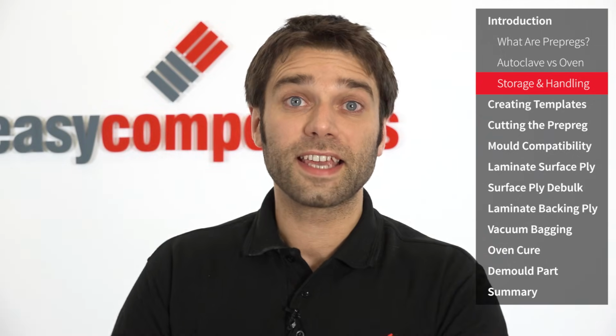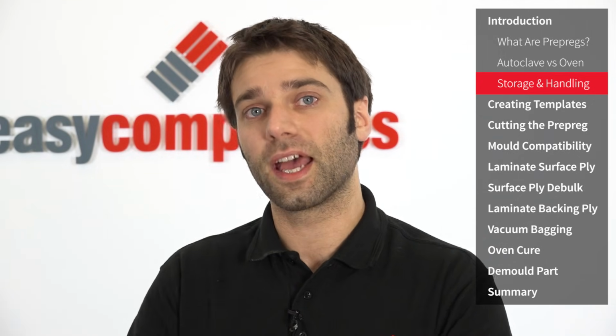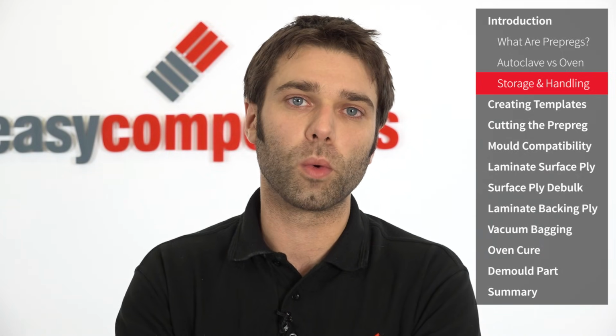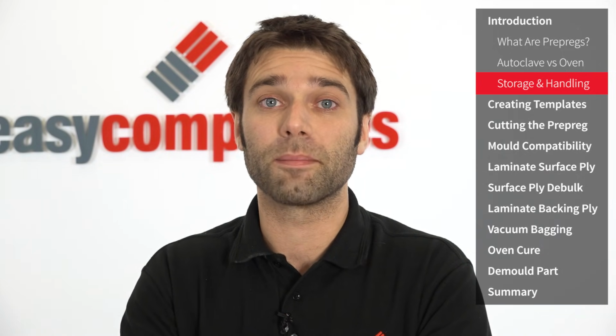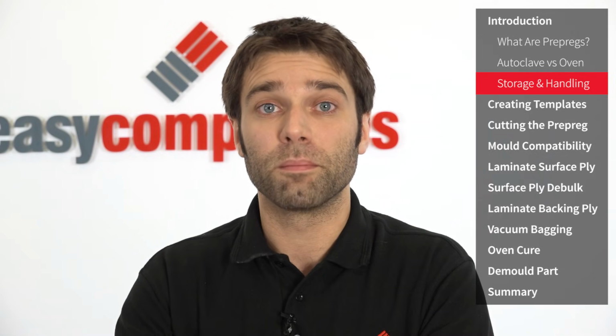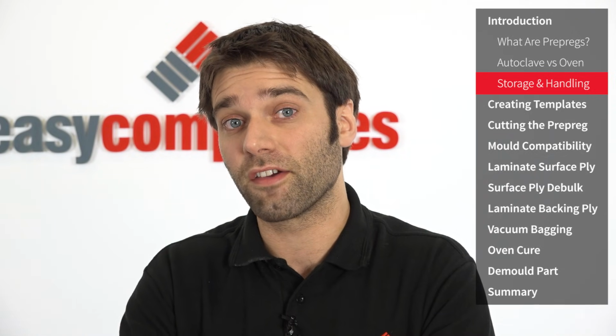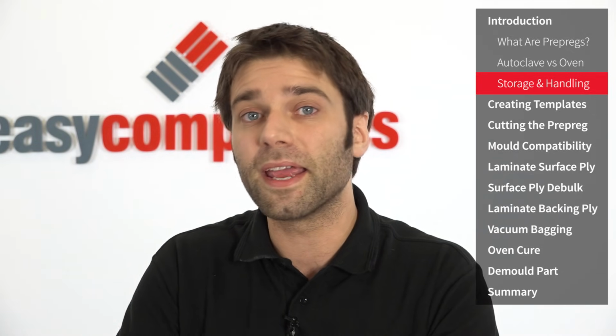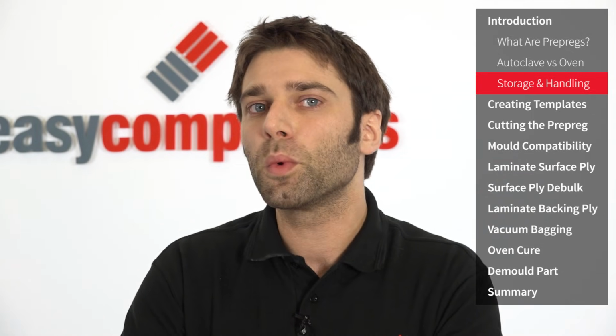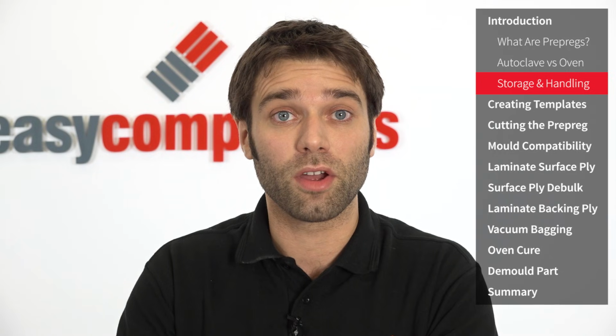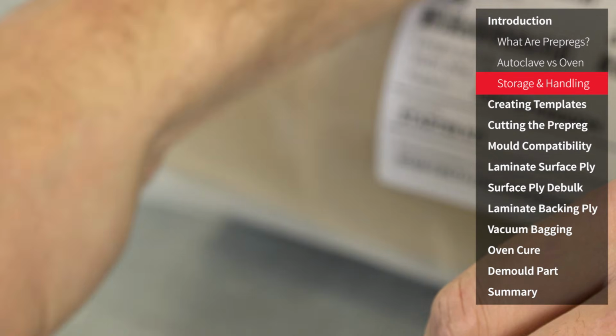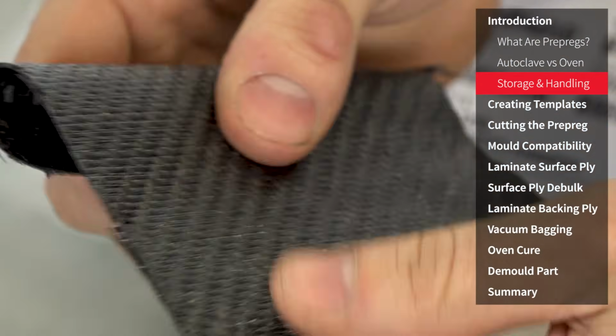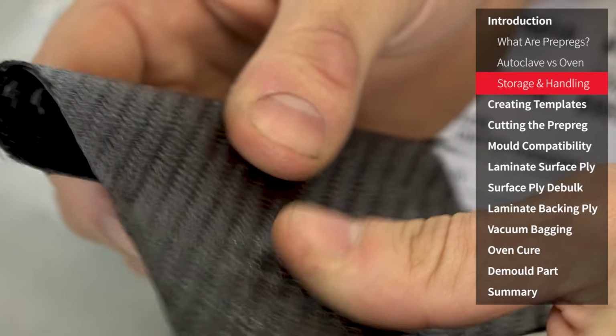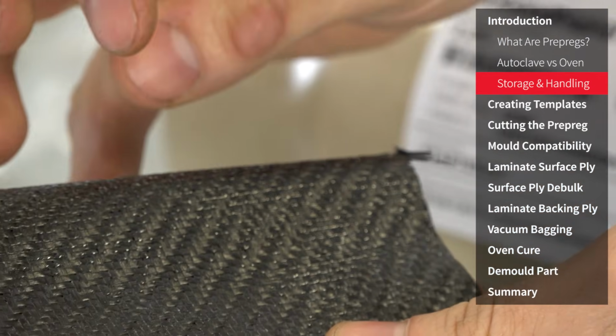In the case of this XC110 system, it has a working time or outlife of 4 weeks, which means that's the period of time it can spend out of the freezer before the resin system starts to deteriorate. So if you're planning to use the material within that period of time, you may never have to freeze it. If you were wondering what would happen if it was left out longer, we've got an example here, which you can see has gone really crispy. This has been out for around about 6 months,